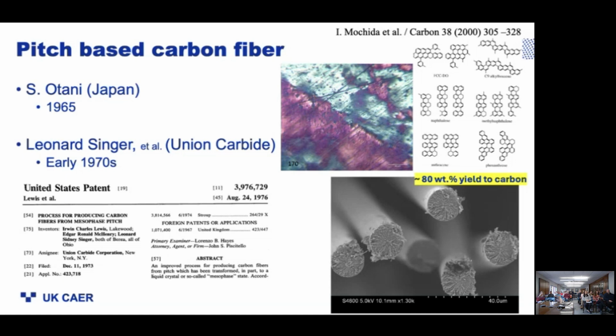Otani showed that he could spin these into fibers and convert those into carbon, and the yields were really high. Something like 50 to 80% of the mass of those fibers would be converted to carbon. So Union Carbide kind of latched onto these results as well and doubled back efforts to try to produce carbon fibers from what they call the mesophase pitch.